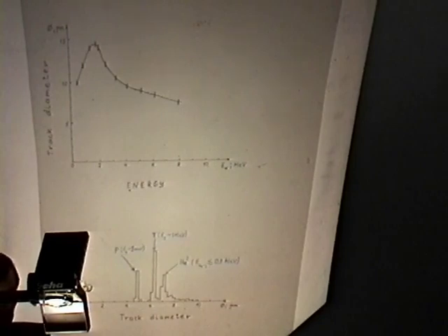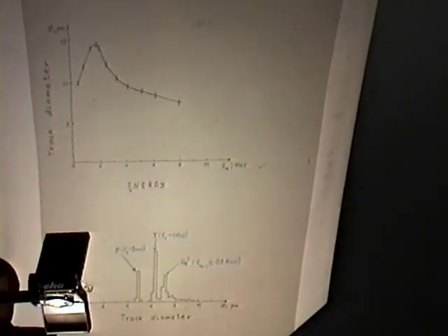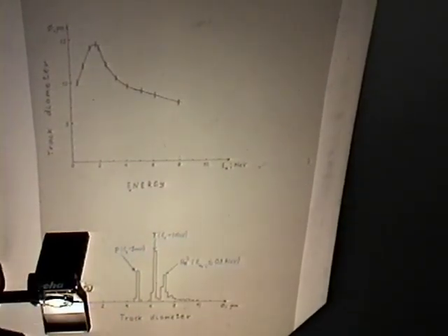The estimation of DD reaction yield by alpha particle measurement is very difficult because, as I noted, the alpha particles from DD reaction outgoing from a thick sample will have energies from 0 to 3.5 MeV, and it is very difficult to measure different track diameters.